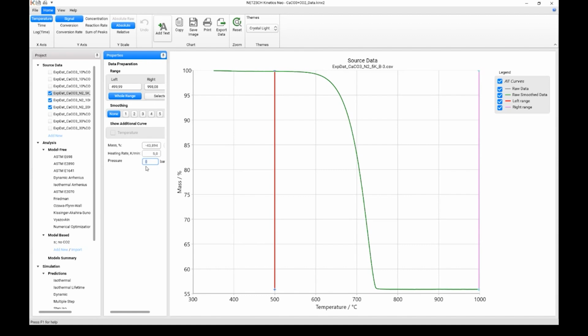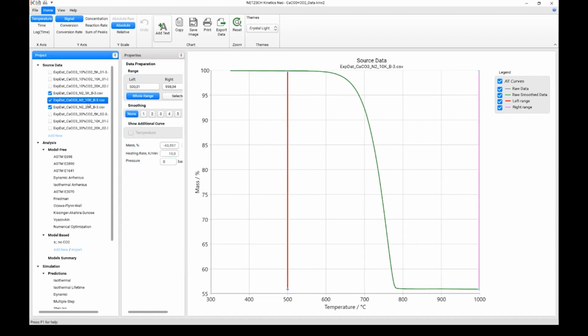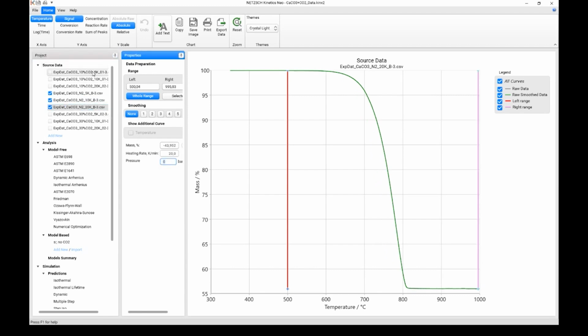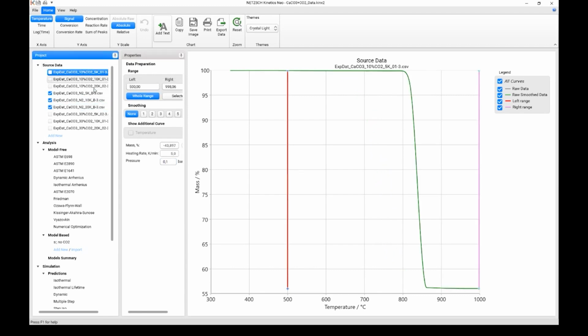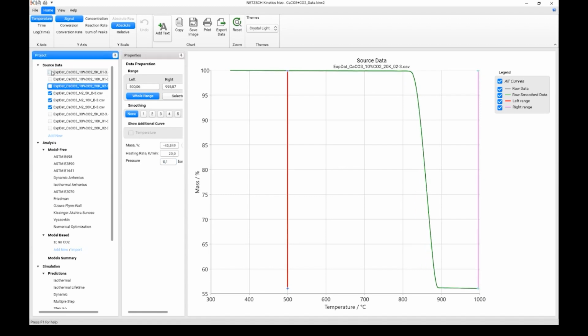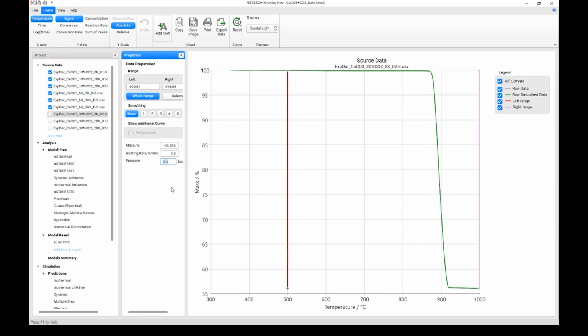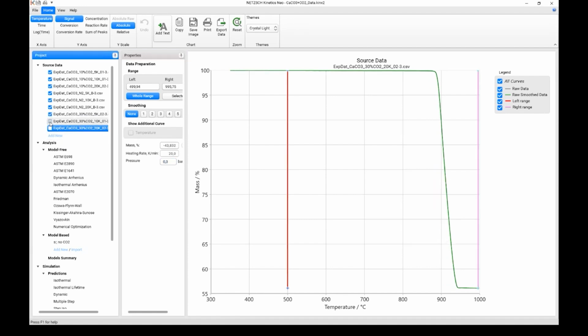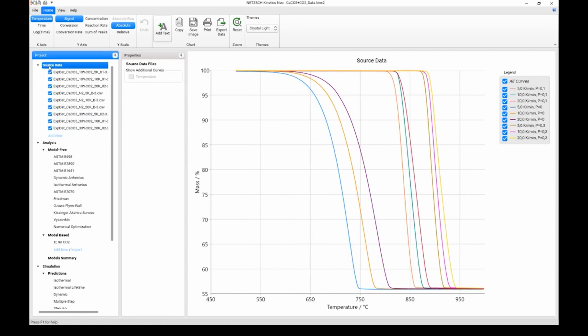Here, for example, for the measurement in pure nitrogen, we have a pressure of carbon dioxide equal to 0. Here, and here it is 0. For the first 3 curves, it is 10% or 0.1 bar. I just switch it on. And for the last 3 curves, it is 30%. Here we see 0.3 bar for the last 3 curves. I just switch them on, and here we have 3 sets of data for the different heating rates and for the different partial pressure of carbon dioxide.